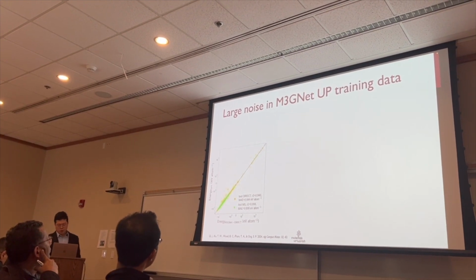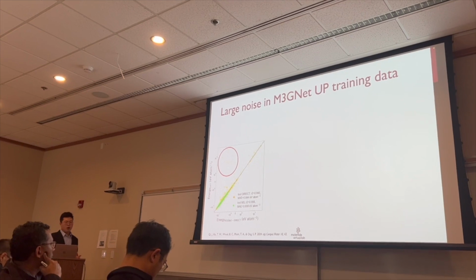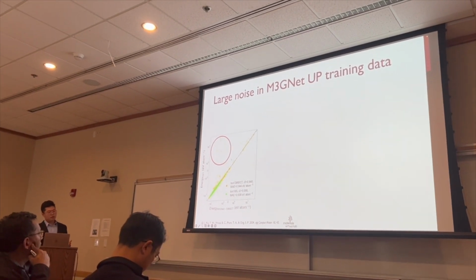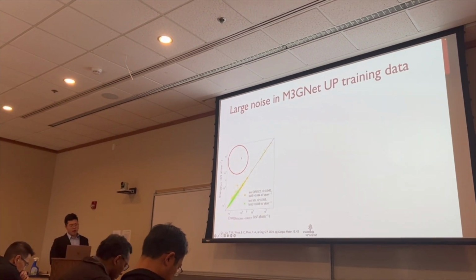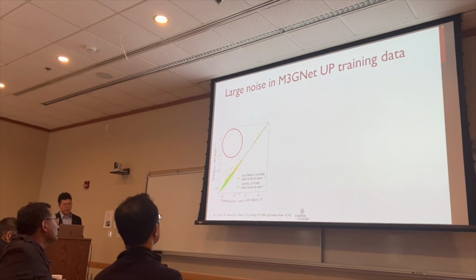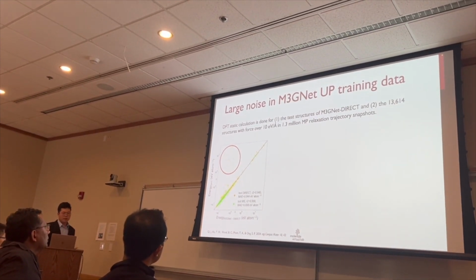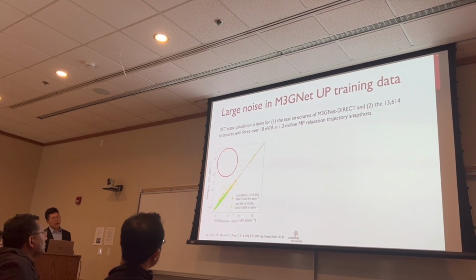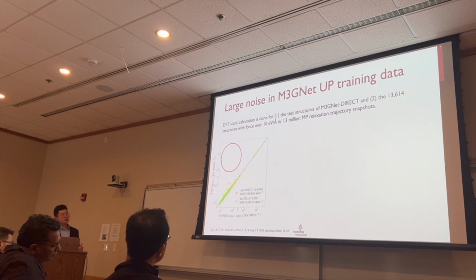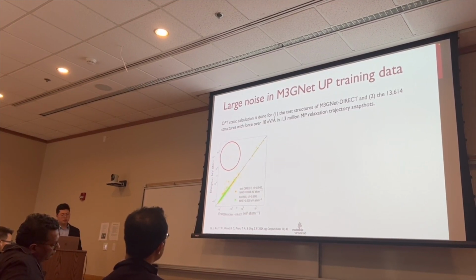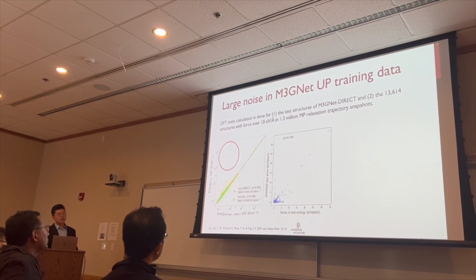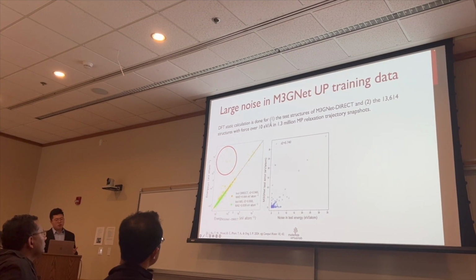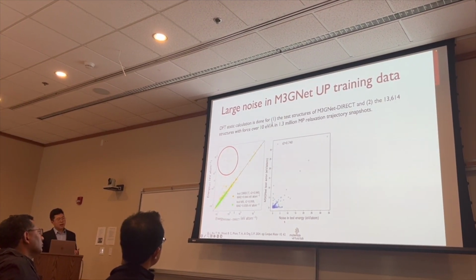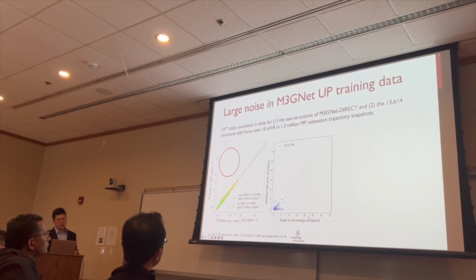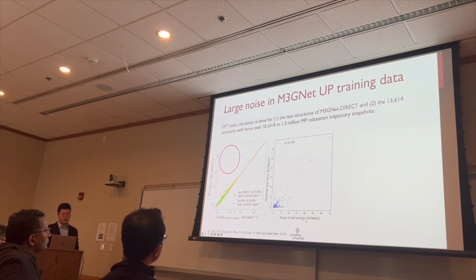And to continue the discussion, I want to show you this plot that I showed before, where we can see that there's some very large test error for M3GNet, which corresponds to more than a few eV per atom error for energy. And this is definitely very large. So that's why we redo the DFT calculation with a static calculation to get the accurate energy and force information to see if this is really an error of our model or actually some noise in the training data. And what we found is that in this plot, we see there is a large correlation between the noise in the test energy, which is the error of the DFT relaxation energy and force against the static DFT energy and force.